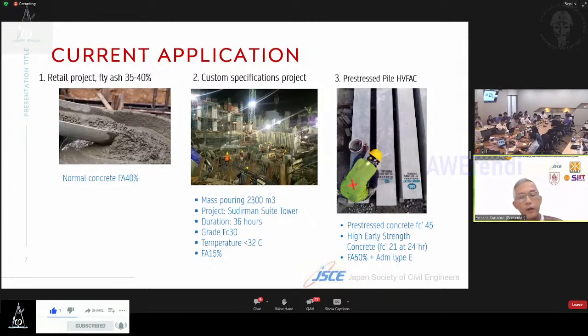So in this condition, we do material engineering by adding chemical admixtures. For this product, we use superplasticizer and accelerator, because we have to reach the strength of 21 megapascal before 24 hours.